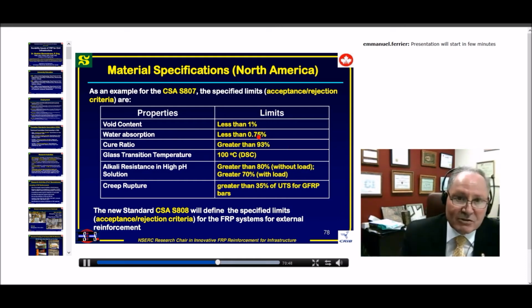Water absorption less than 0.75%. Most of them are getting that. Of course, I'm telling you this is for the internal reinforcement. You will see later when we talk about external reinforcement, we don't have the same numbers at all, because the manufacturing process is not the same. We are having lower values with the factor and so on. Anyway, water absorption, cure ratio, glass transition temperature, and alkali resistance greater than 80%, 70%.